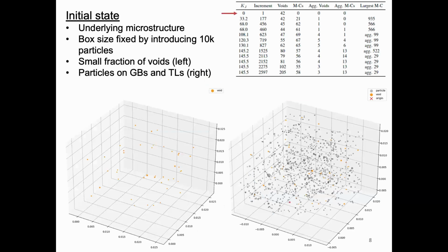And some example of how it works. This is just one picture that is followed. This is at an integration point ahead of a crack in a 3-point bend specimen. And this is the load here that you see, the stress intensity factor that is increasing. I think these are the number of voids. These are the increments in the solution. Number of voids, number of microcracks, aggregate voids that are formed by coalescence, aggregate microcracks, and so forth. And the simulation starts with a random distribution.